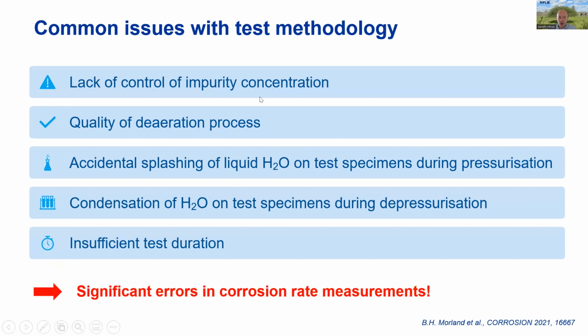There's a lack of control of impurity concentration. These impurities can react together. They can be consumed in corrosion reactions, and they can be lost through evaporation, for example. So it's very important that throughout the whole duration of the test, the impurity concentration is controlled properly. Secondly, we need to remove any influence of oxygen by deaerating fully the autoclave.